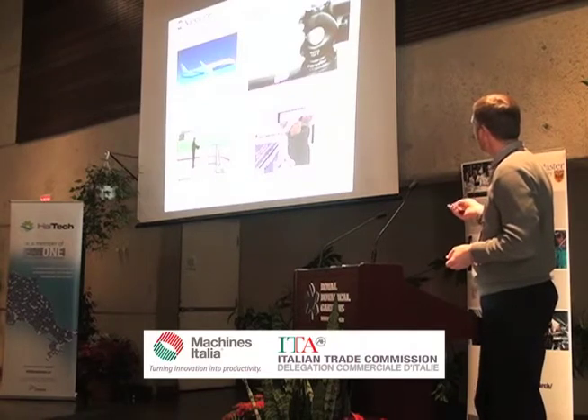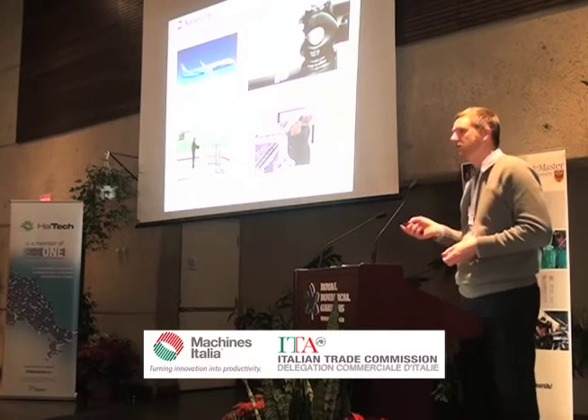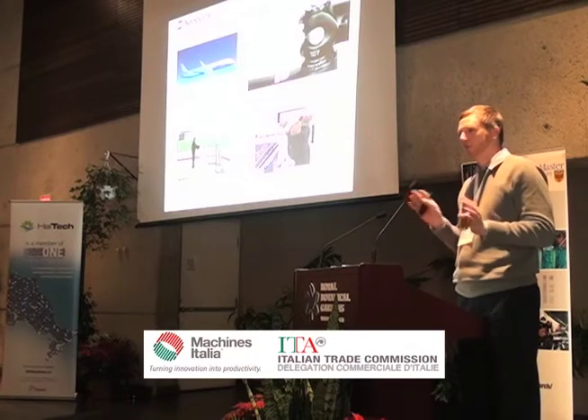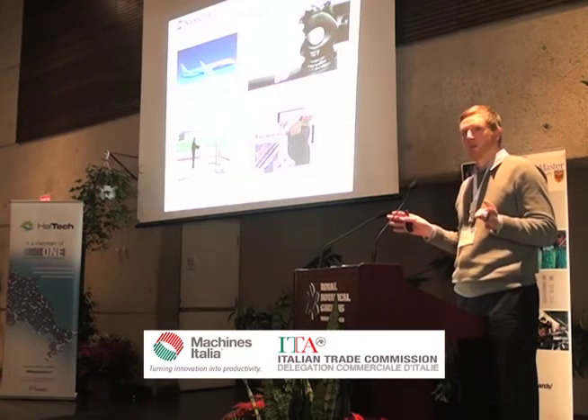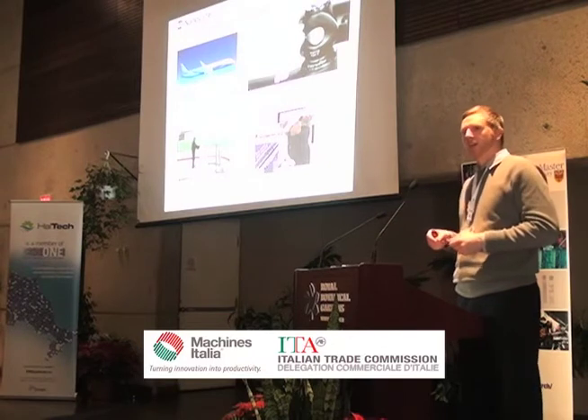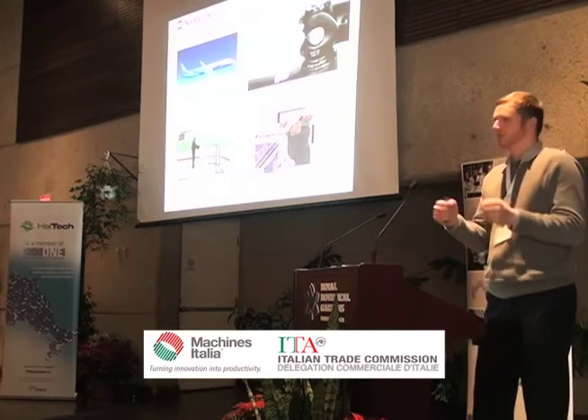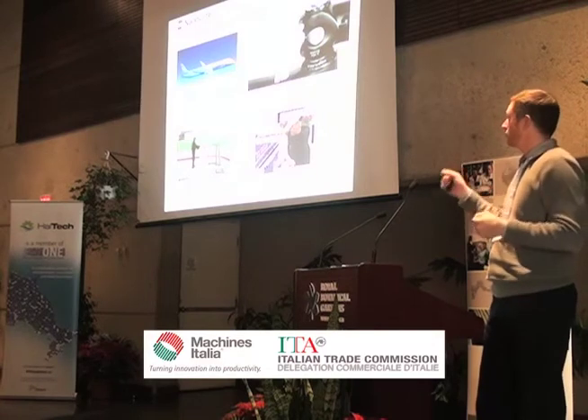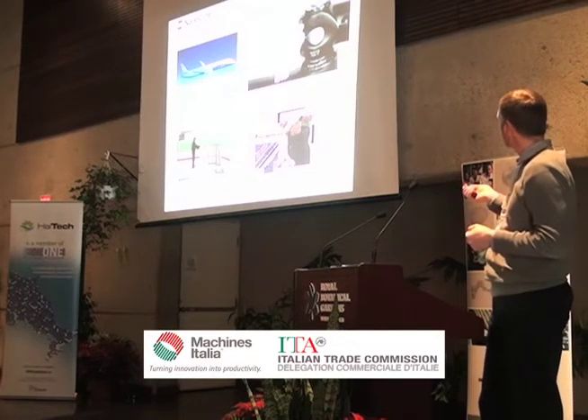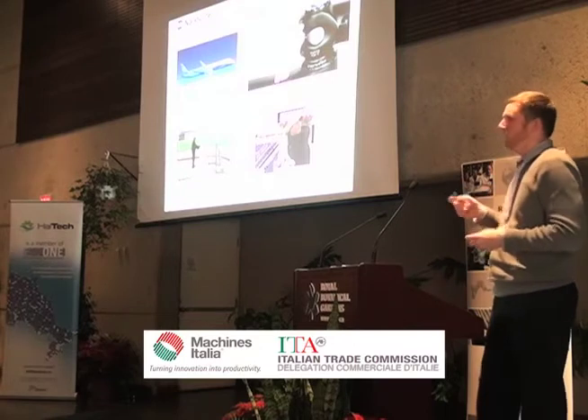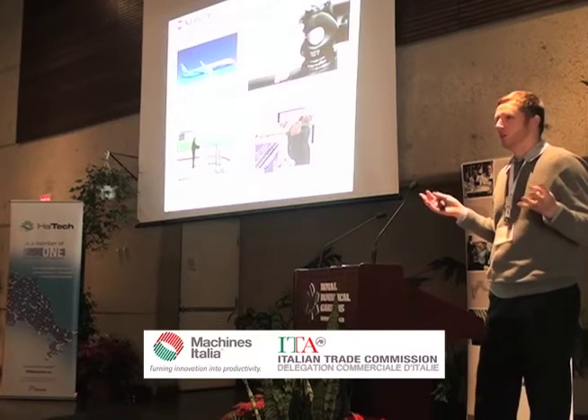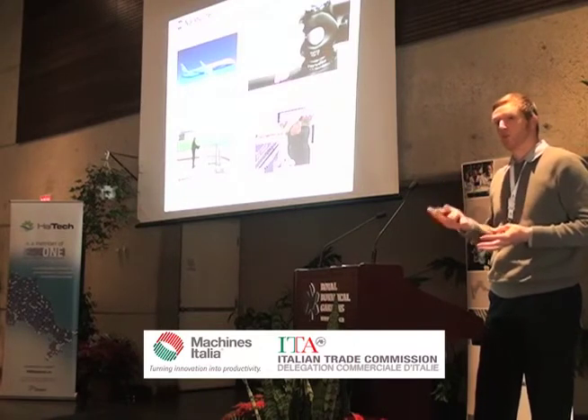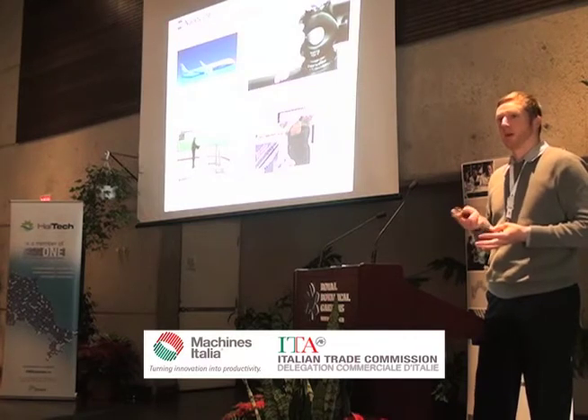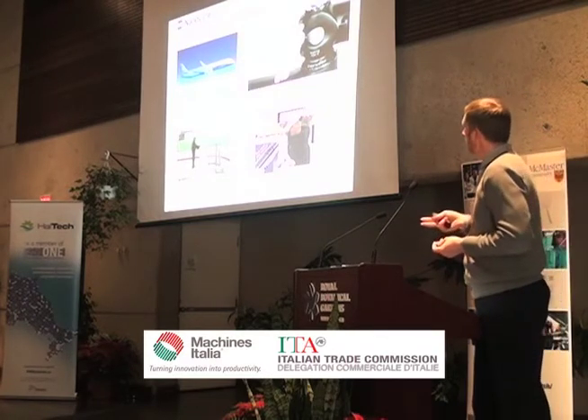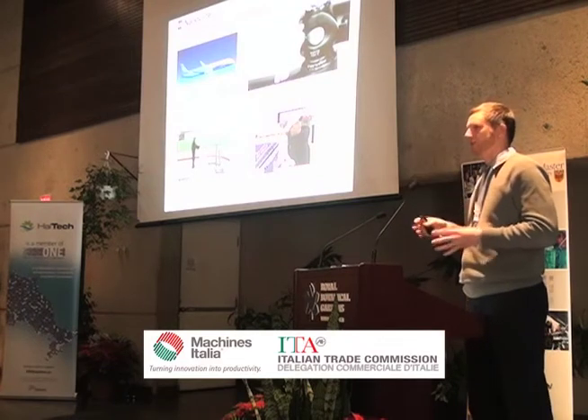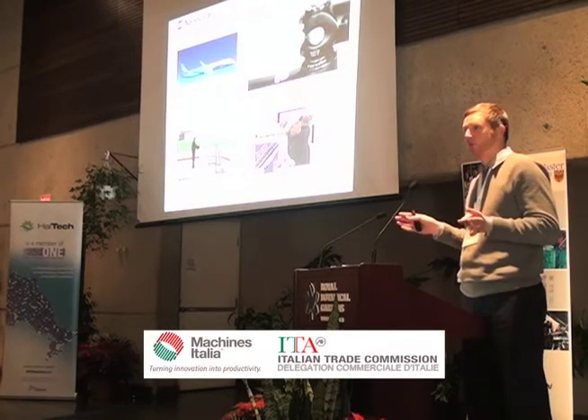The folks at Cervelo here came to us because they had a composite steer tube on their very lightweight, very high performance composite bike, something that'll sell for like 10 grand. You take that steer tube and you hit something while you're riding it, and there's a subcritical impact introduced right into this area here. You then undergo some sort of fatigue test, and you don't know when it's going to fail, but you know it's going to be less than its unimpacted version. So they were finding that this part would fail after like 2,000 cycles or so, on average, after an impact.